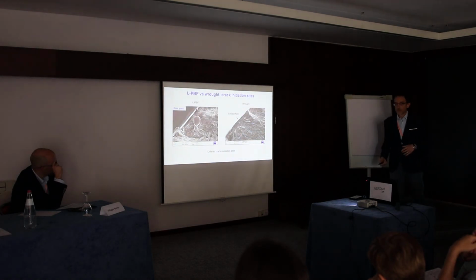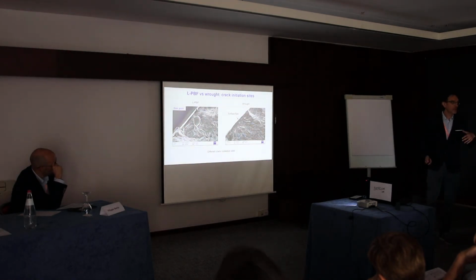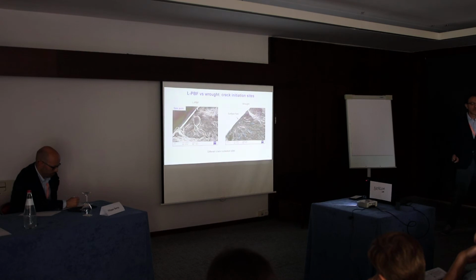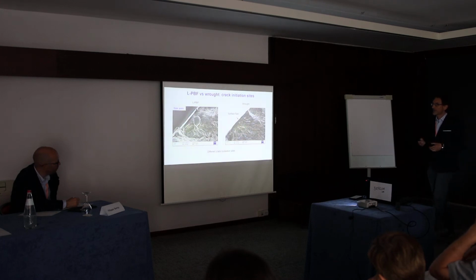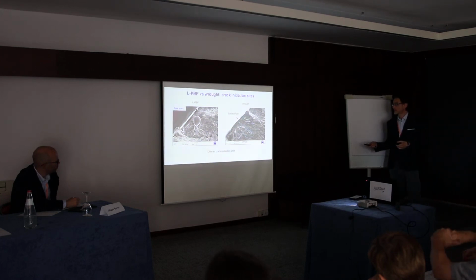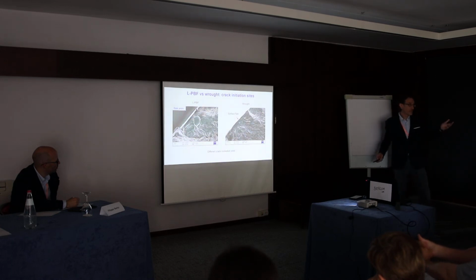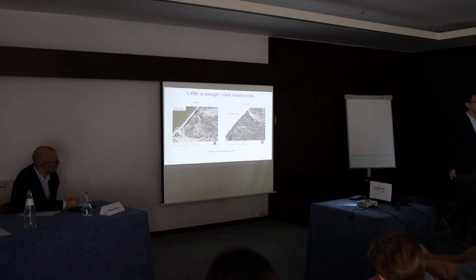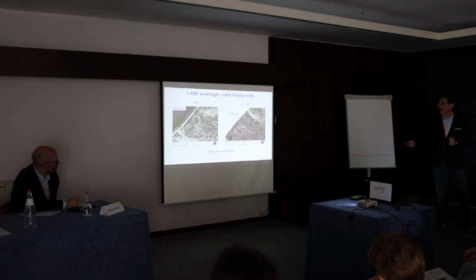And so I want to conclude my presentation just showing you another picture concerning the difference in crack nucleation size. As expected, for the additive manufactured material, crack nucleation occurs at internal defects like pores or lack of fusion defects, which I showed you before. By contrast, for the raw material, a typical crack initiation site is at the surface, at a surface flaw.